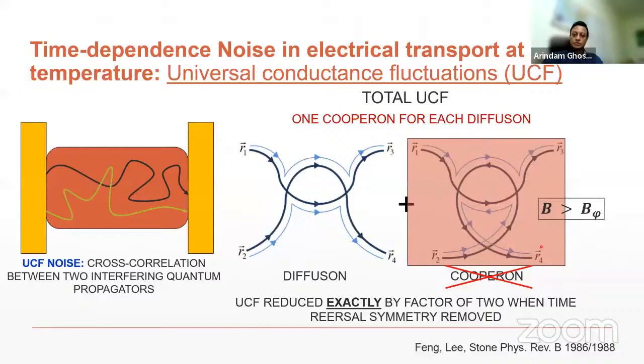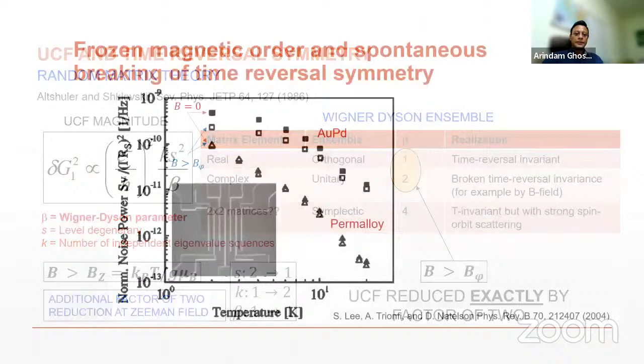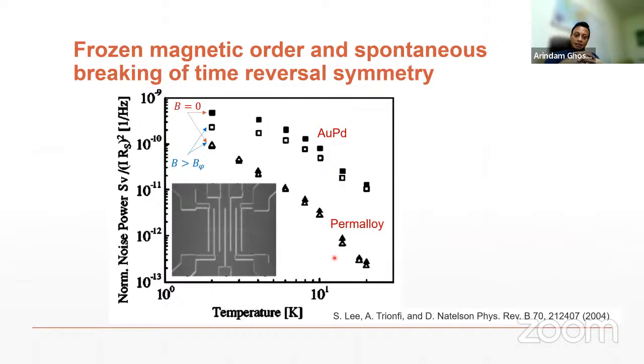So this has been used by early measurements in magnetic wires. For example, this was Dr. Natelson's work in 2004. You can see if I take a gold palladium non-magnetic wire, if I apply a magnetic field which is larger than the phase-breaking magnetic field, noise comes down by a factor of two. So from here, it comes down here.